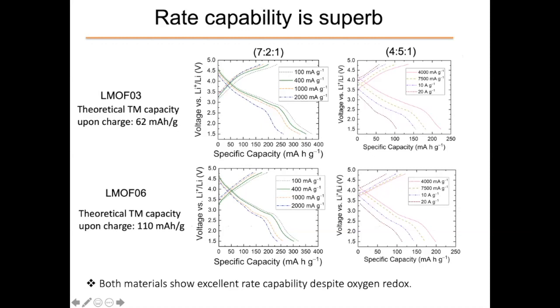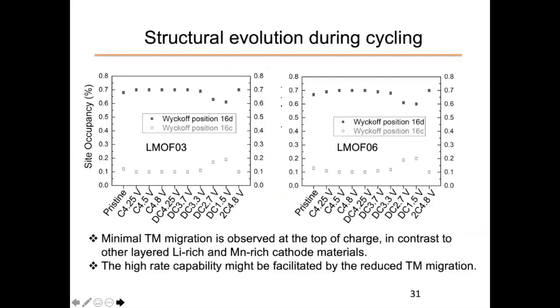If we dilute the electrode to have less active mass and more carbon, we can even get to 20 amperes per gram, clearly showing that these materials are not intrinsically rate limiting. And so while early DRX materials had low rate capability, some of these newer materials clearly can show very high rate. These materials do not undergo a lot of change during cycling.